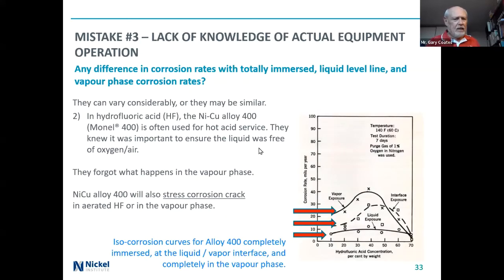A second case is in hydrofluoric acid, a very, very nasty acid, and we know because the nickel copper alloy 400, which is the most common alloy used, or one of the most common alloys used for this service, it's important to ensure the liquid was free of oxygen. The company knew that, but they didn't think about the vapor phase.